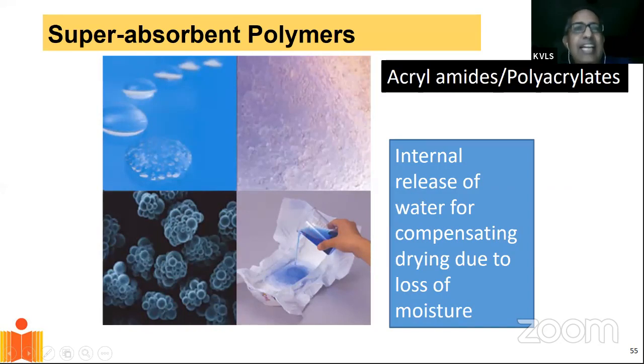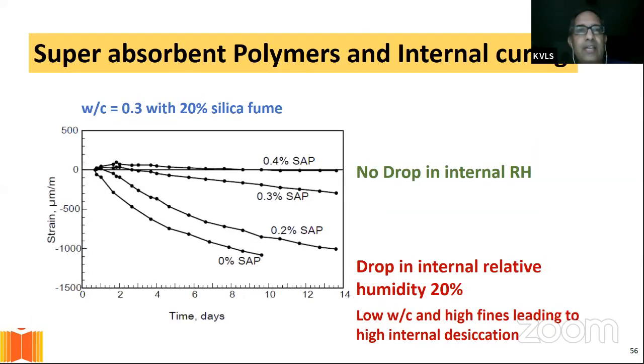So now we are basically adding these super absorbent polymers into concrete so that they can release water to concrete when it is required. And concrete shrinks because it dries. So now, whenever I subject concrete to drying, if I can supply the water from the inside from a superabsorbent polymer, I can keep it from shrinking. So now superabsorbent polymers are being used by mixing them into concrete so that I can reduce the risk of shrinkage.